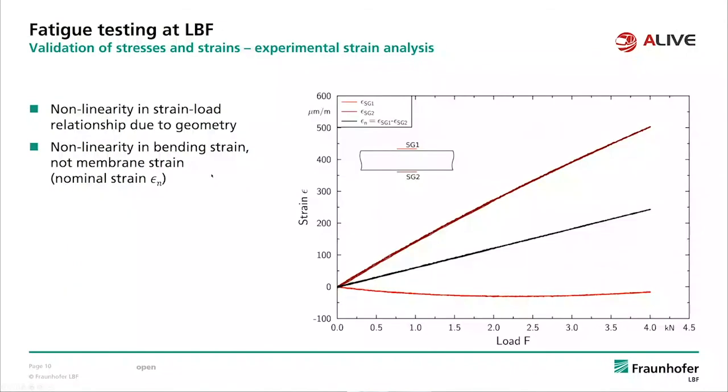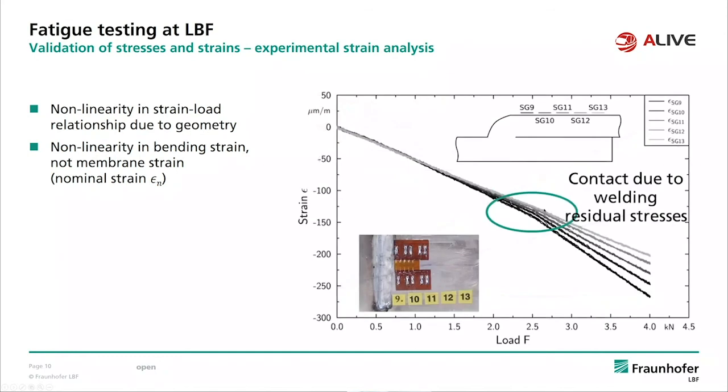Now looking at what can happen, and here is also quite an important phenomenon that, if it is not considered, for example in a finite element analysis, you can get different results between your simulation and your reality, because you see a nonlinearity due to geometry. So a nonlinear relationship between the strain and the load. So this is important to really identify and consider in your further evaluations. Finally, we get something like this. So a quite interesting specimen.